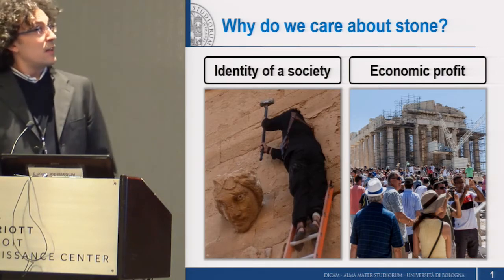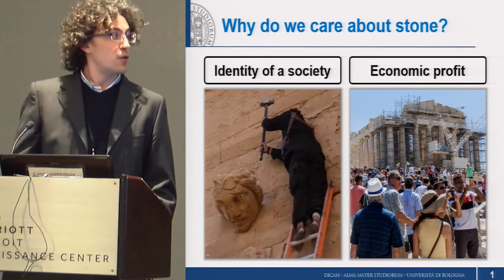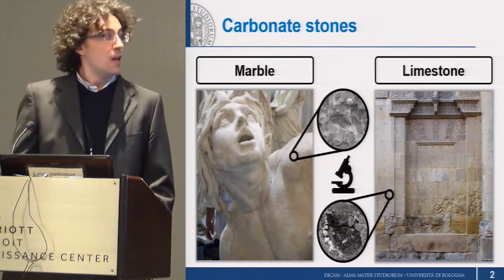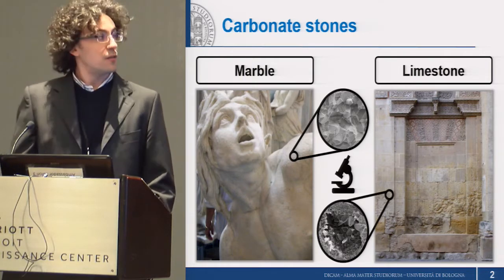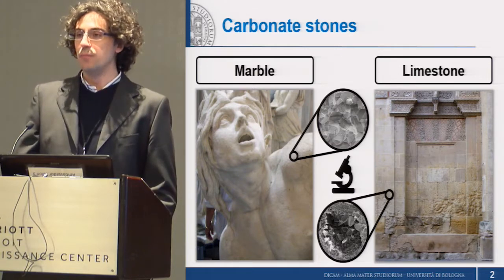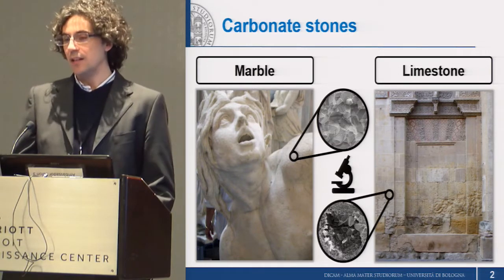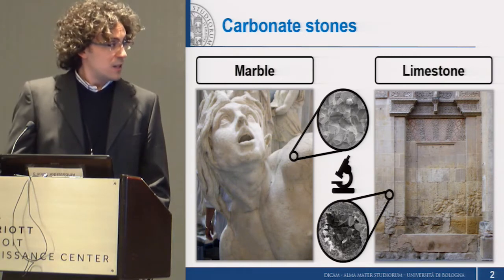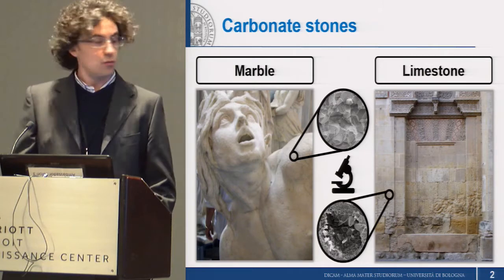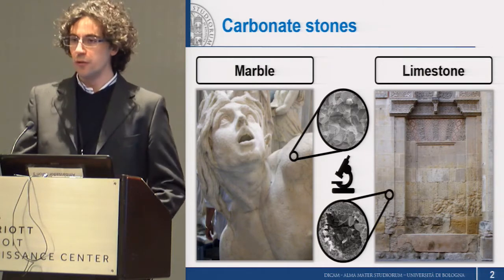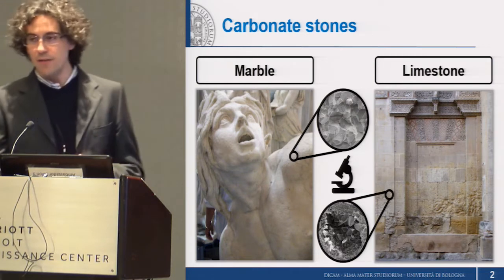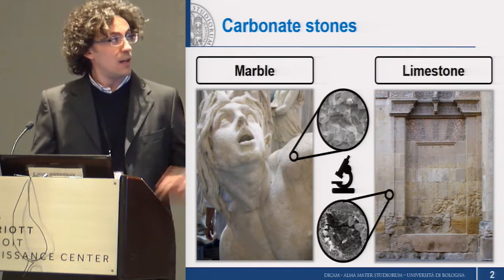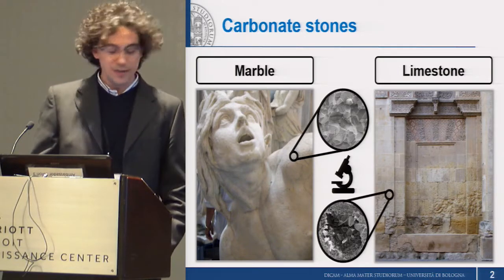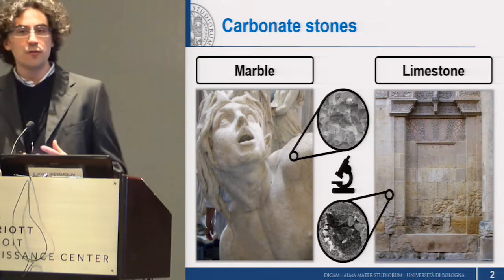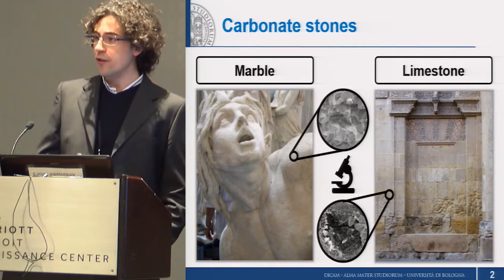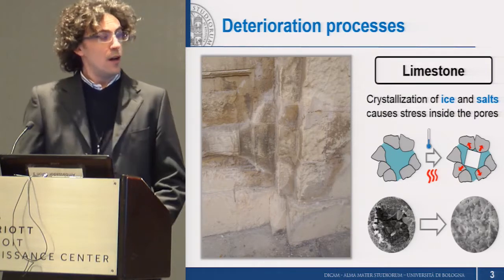So among the stones used in cultural heritage, the most diffused ones are carbonate stones, mainly marble and limestone. These two stones have basically the same mineralogical composition, that is calcite up to 100%, but what is significantly different between these two lithotypes is the porosity, the microstructure. Marble is basically non-porous, so it has very tightly packed grains, while limestone may have a porosity up to 40–50%. As a consequence of the different microstructure, the deterioration processes that these two stones undergo are also quite different.